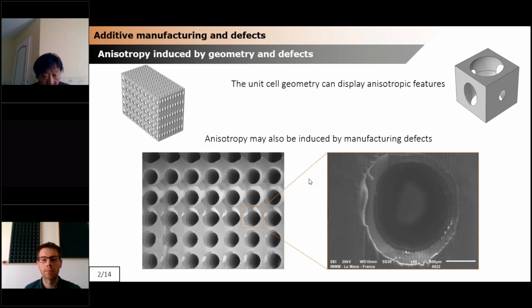Okay, I will now cover some problems related to defects and anisotropy. We've been talking a bit about anisotropy this morning. I think Cami involved it in the homogenization process, and also Thomas with the valve ball, which actually is kind of a selective anisotropy. You can imagine this very simple unit cell, which has different size poles on the different directions. And we tried to actually print those samples. On the picture on the left side, what you actually see seems pretty much the same as the idealized unit cell.